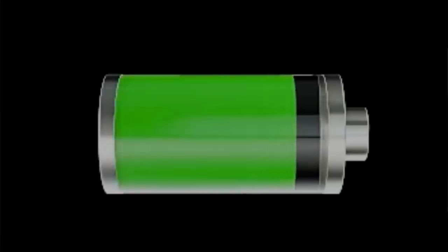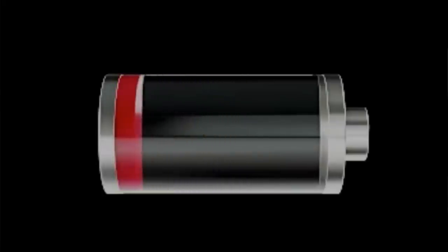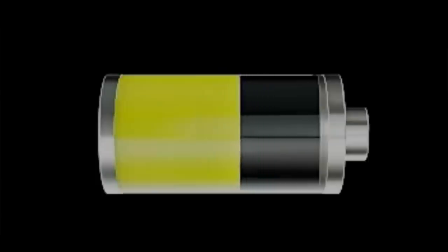There are two battery chemistry developments that will take Tesla well beyond 4,000 cycles. In the earlier days of lithium-ion batteries, fully draining to zero and charging to 100% put the most stress on the battery materials, worsening cycle life. It turned out that keeping the battery between 40–60% state of charge gave maximum cycle life, because you weren't straining the underlying materials inside the battery.